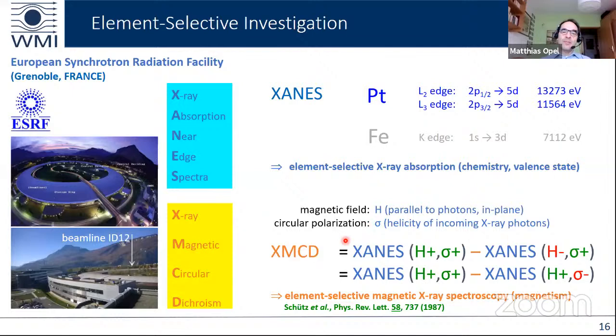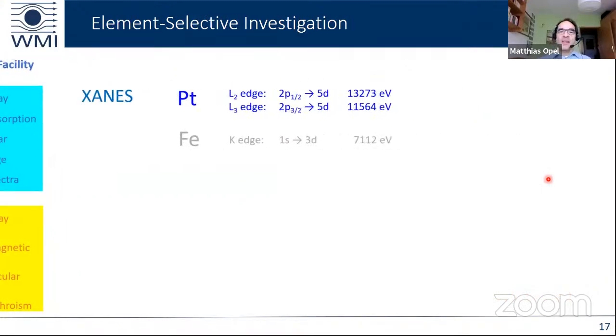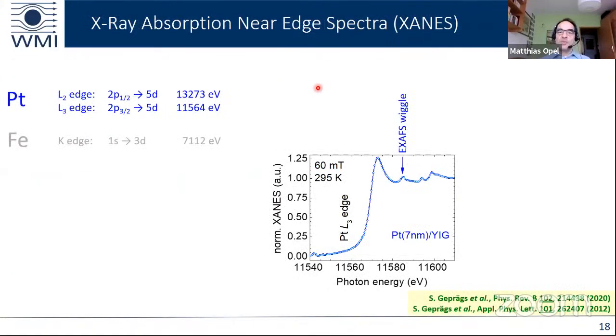And with those, one can measure or calculate the magnetic dichroism by obtaining an X-ray absorption spectrum at positive magnetic field and positive helicity minus the X-ray absorption spectrum at negative magnetic field and positive helicity, or at positive magnetic field and negative helicity. So with this XMCD, you obtain some information about the magnetism of the samples. With the X-ray absorption, you obtain information about the chemistry and the valence state of the samples. So let me first start with the X-ray absorption.